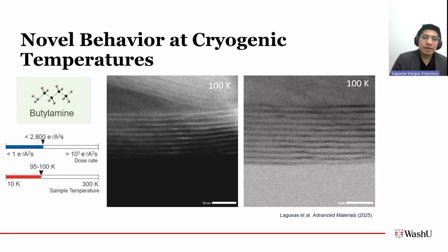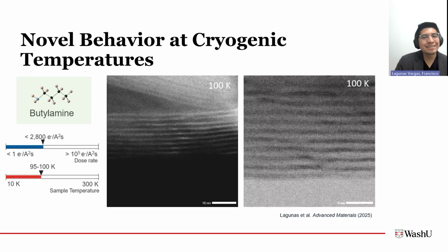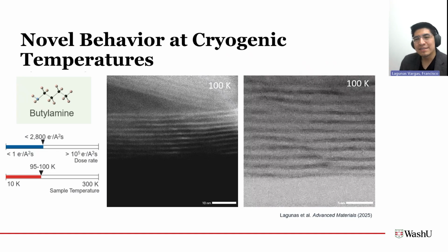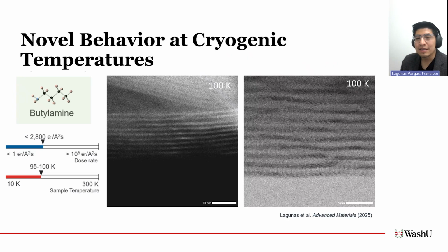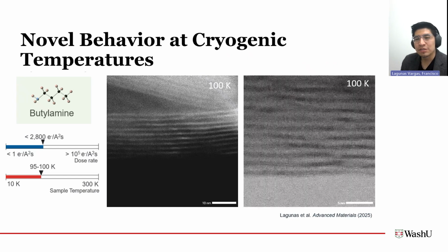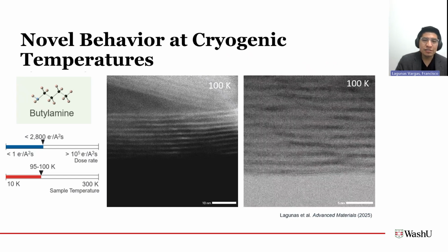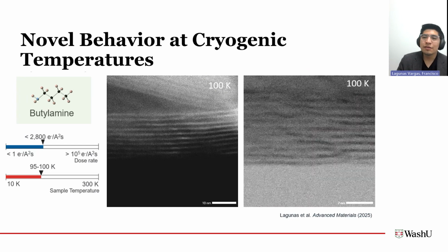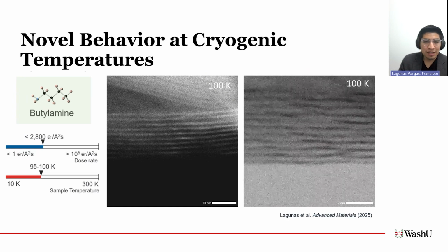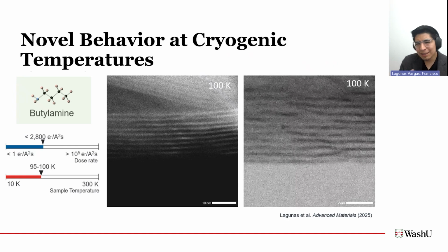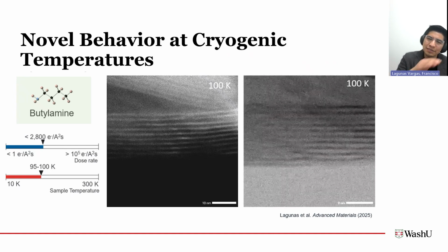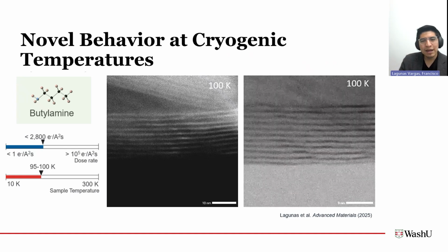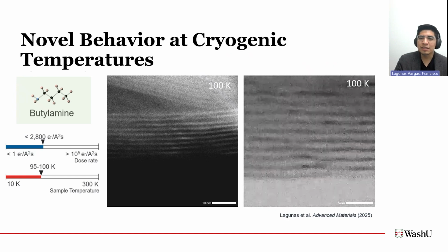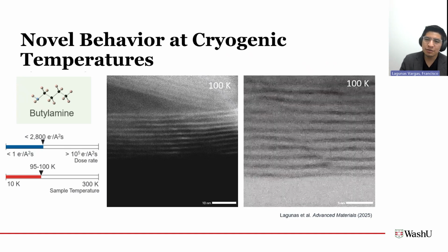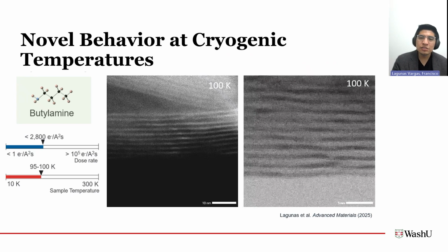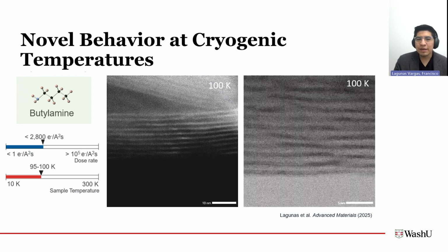Okay, so now we can talk a little bit about some of the defects that we see at room temperature, or in these hybrid MXenes at cold temperatures. So a couple of slides ago, I showed that if we're imaging with enough electrons to acquire atomic resolution imaging, the materials don't really look that different from what you would expect. You have these layered structures, and between them, you have these dark regions with your organic material. And if we put a lot of electrons into it, maybe we can start seeing some small modulations, but we don't see anything very dramatic.